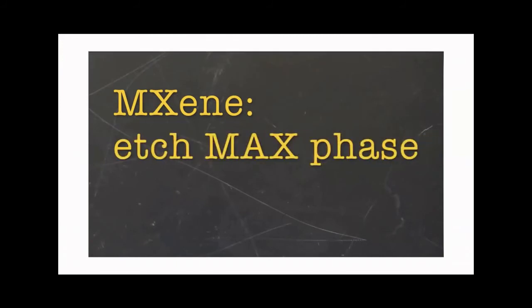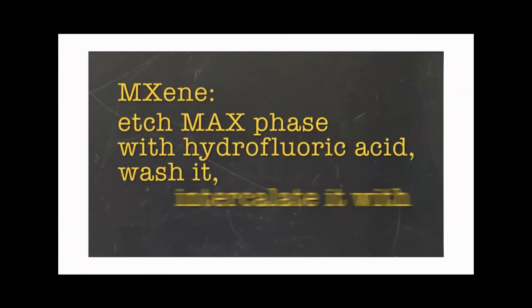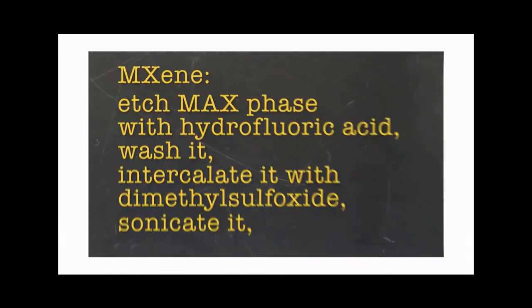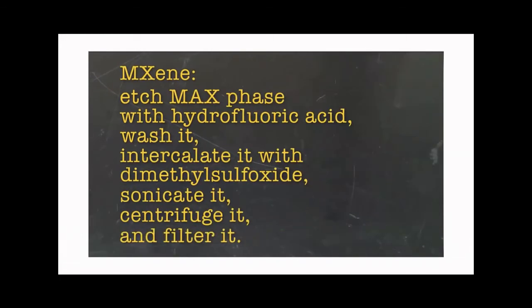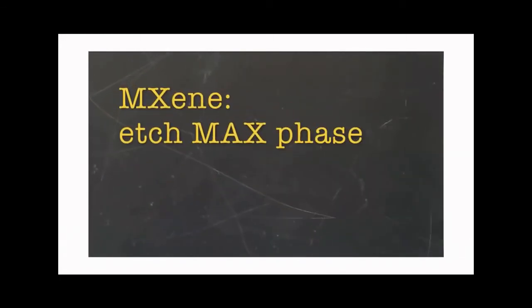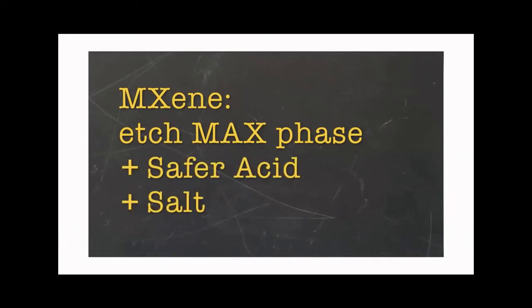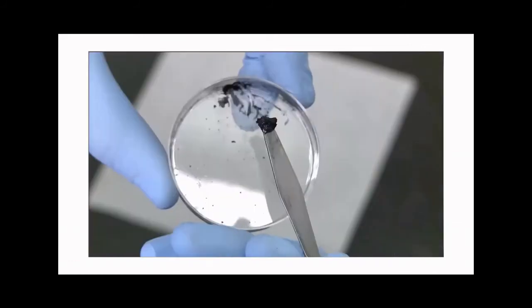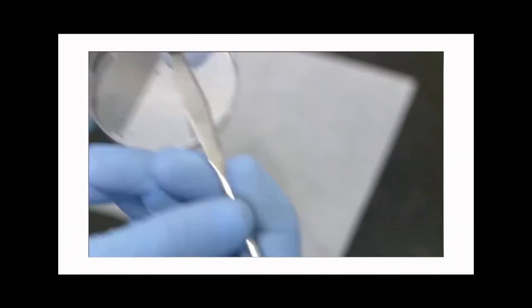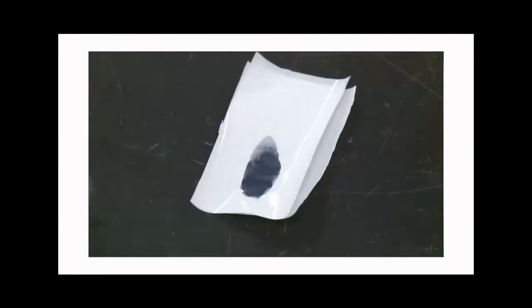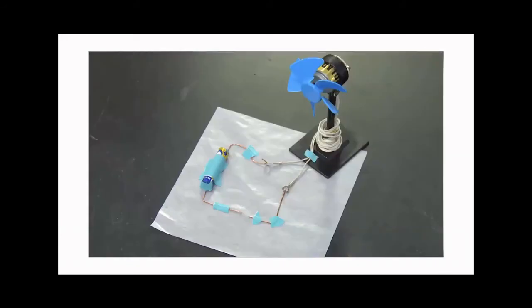In the past, to create pure MXene films, you'd have to etch MAX phase with hydrofluoric acid, wash it, intercalate it with dimethyl sulfoxide, sonicate it, centrifuge it, and filter it. We've managed to cut the process down to just the etching step. Now, we simply react MAX phase with an etchant made from much safer acid and a salt, and after washing, we're left with a clay-like material that we can shape any way that we want, even rolling it out into a film. After drying, it's highly conductive.